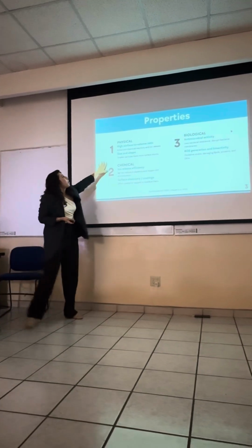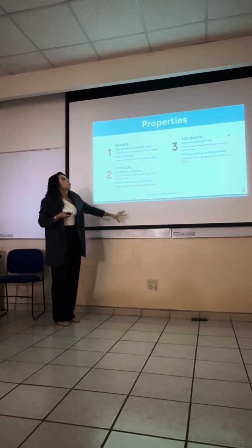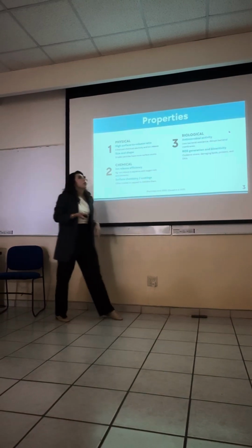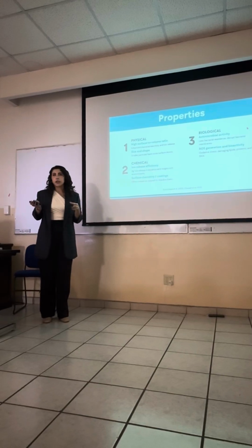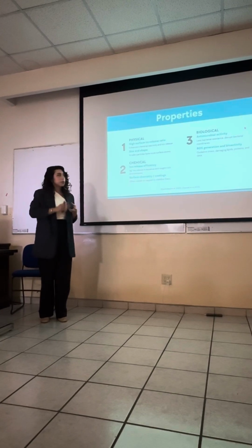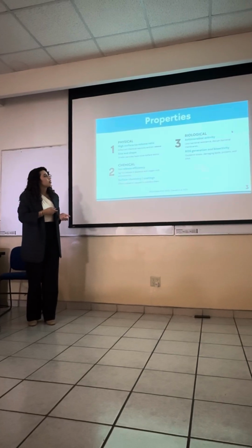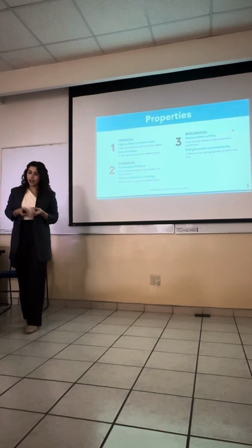And these properties set up the base for the biological properties, of which the most relevant, as I said, is the antimicrobial activity, which basically means that the silver ions cause bacterial membrane disruption and the generation of reactive oxygen species, which cause oxidative stress and damage lipids, proteins, DNA, etc.